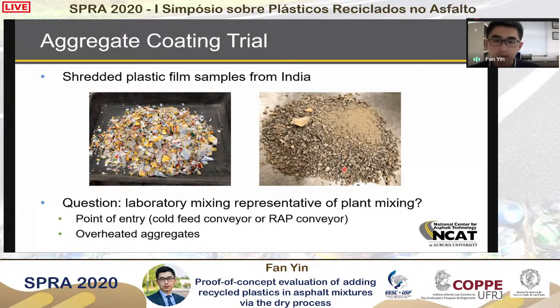Where the recycled plastic can be introduced. Are we introducing it using the cold feed conveyor, or are we using the RAP conveyor or around the RAP inlet into the drum plant? Depending on where we are introducing the recycled plastic, it's going to be exposed to very different thermal history inside the drum. And also the interaction or the melting of the plastic depends on the aggregates, the temperature of